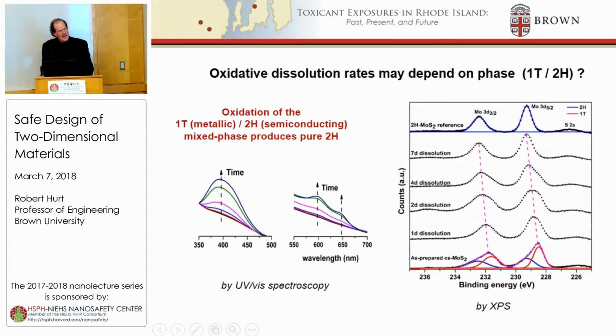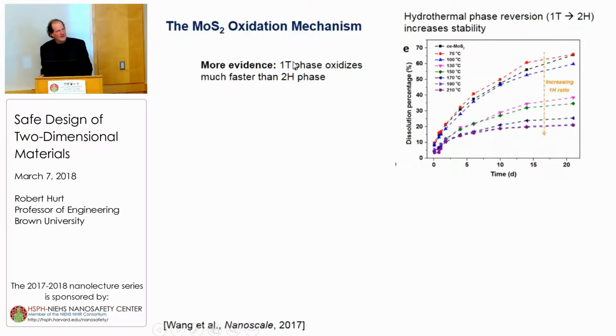The original chemically exfoliated material can be deconvoluted into a mixture of metallic and semiconducting. You see the peak deconvolution. Over time, as you start to oxidize it and dissolve it, you see peak shifts to the left and changes in peak shape. If you deconvolute the spectrum, you can see you're headed toward the pure 2H semiconducting phase. And optical data gives you the same result. So it seems like this 1T phase oxidizes faster than the 2H semiconducting phase.